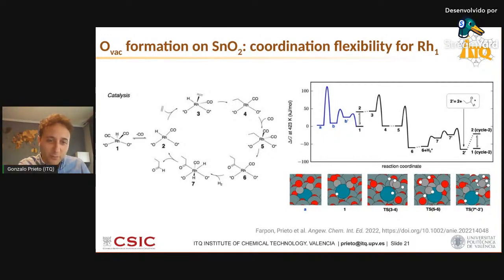And the mechanism goes as follows, bear with me, along the cycle from 2 to 7. From 2, to create 2, actually, this coordination-flexible metal center can lose one of the CO ligands energetically relatively easily. That's one of the keys for this mechanism. And this is something that also happens, but with phosphine ligands rather than CO, in homogeneous catalysts, or in molecular catalysts following this mechanism in solution. Then ethylene adsorption in 3, ethylene insertion into the rhodium hydride bond in 4, further CO coordination and migratory insertion into the ethyl rhodium group to lead to species in 6, then it's just hydrogenation and reductive elimination from 7 to produce propanal and close the cycle.